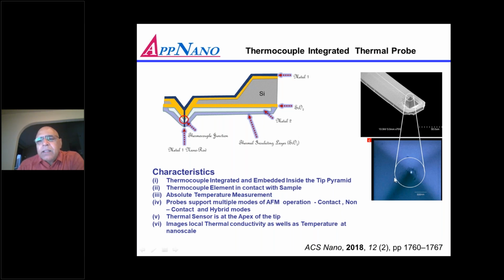you are scanning. And this nanorod, when you see from this focused ion beam image, where I can have a good contrast with the nanorod and the oxide tip, the shining bright spot is the nanorod. So this is at the apex. So you are always scanning your sample with this nanorod. So whether you are in a contact mode or non-contact mode, your nanorod is always in contact with the sample. It means in contact with the thermal properties of the sample.